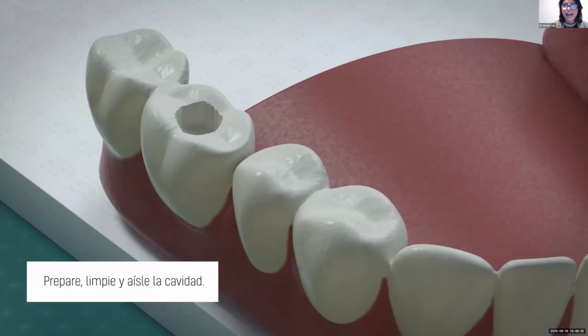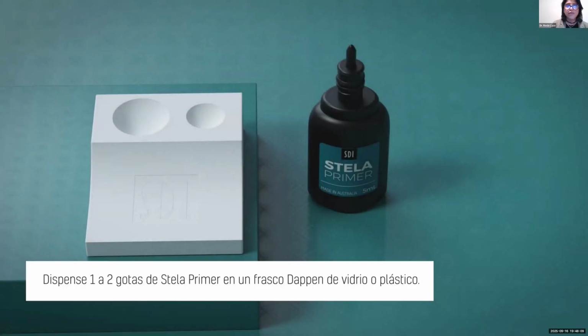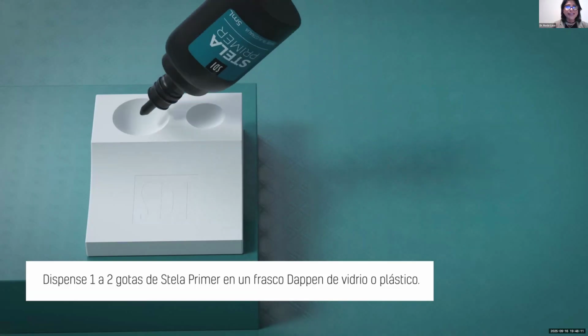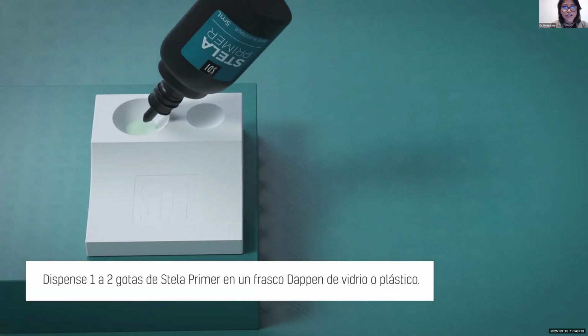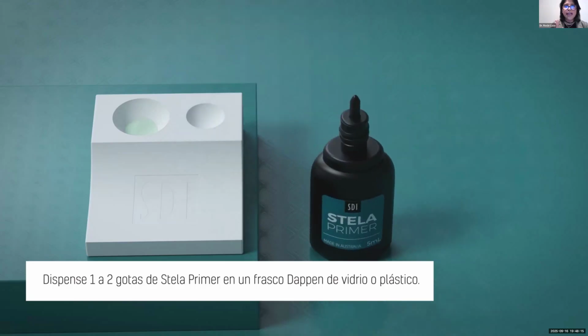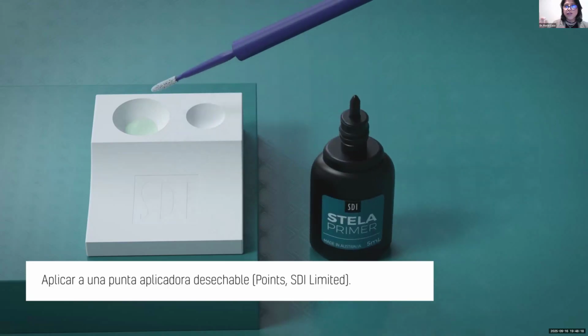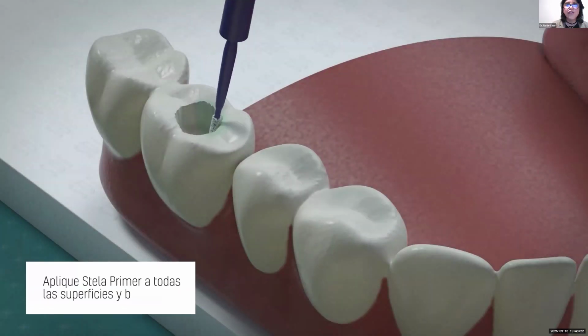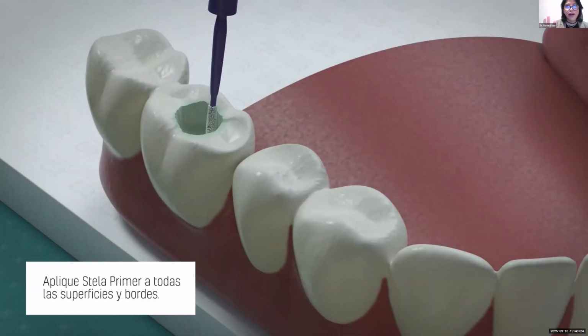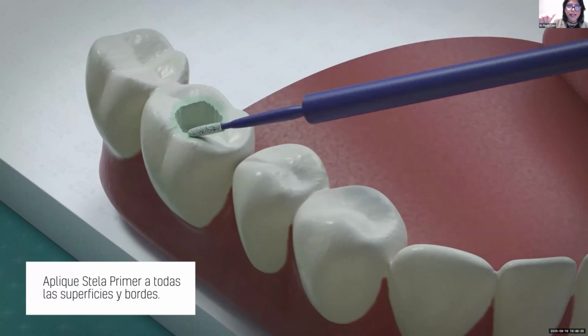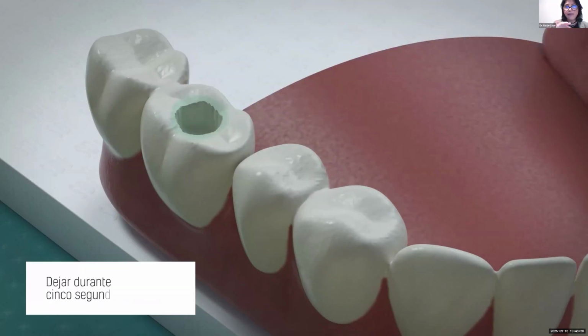Okay. You have a cavity in dentin, you prepare your cavity, selective carious removal, remove all the infected dentin and work in affected dentin. It's ready, your cavity. So your first step is use Stela Primer. You apply Stela Primer and, okay, wait for 5 seconds. After 5 seconds, you can dry 2 to 3 seconds, okay?